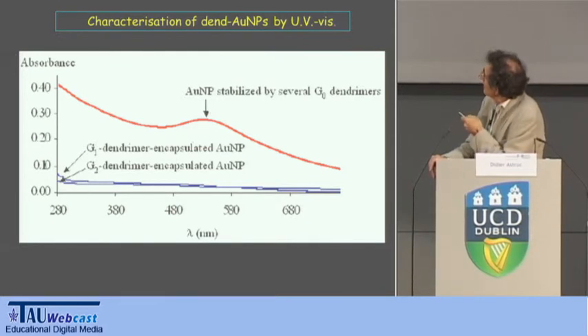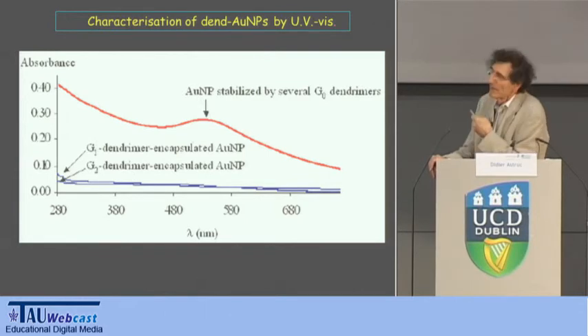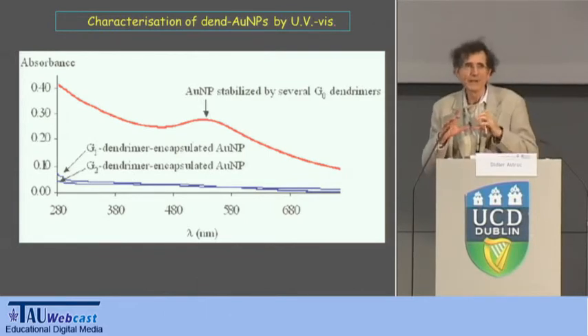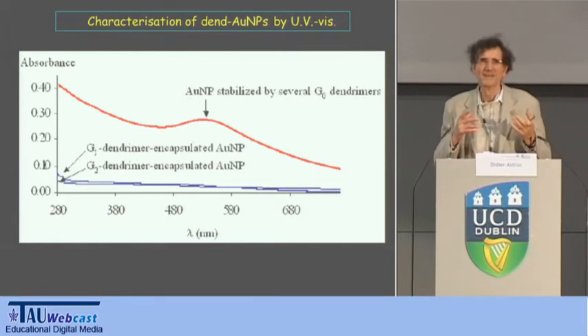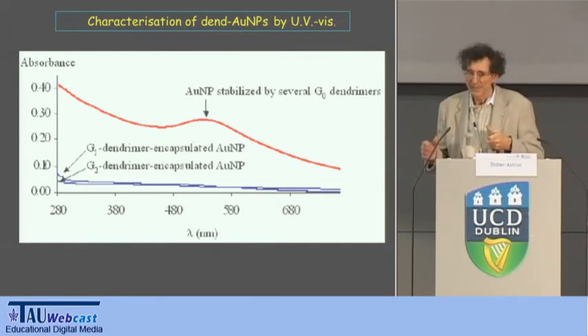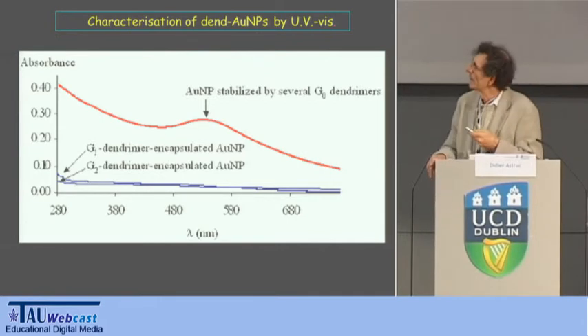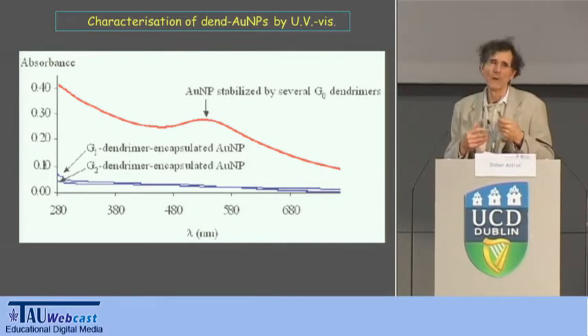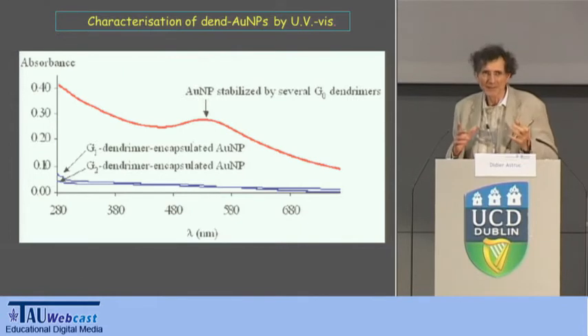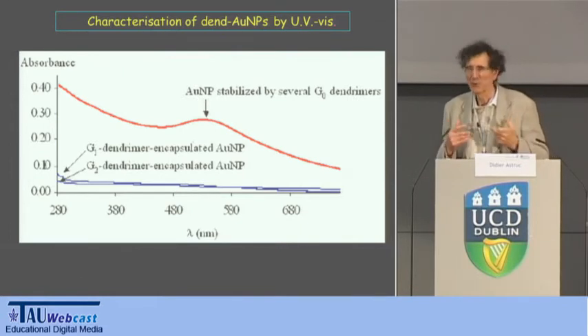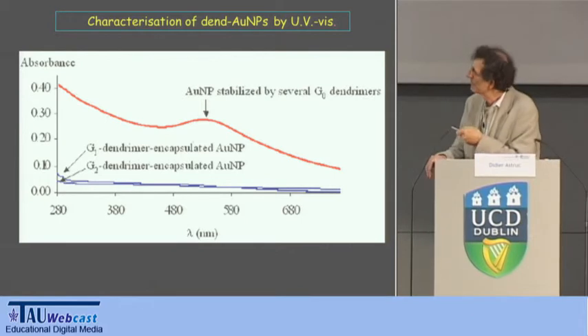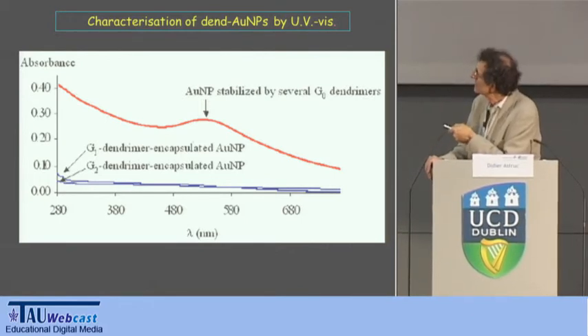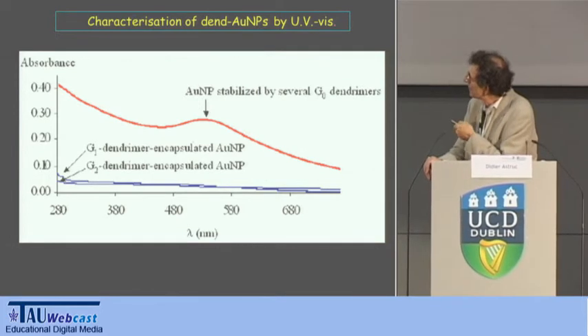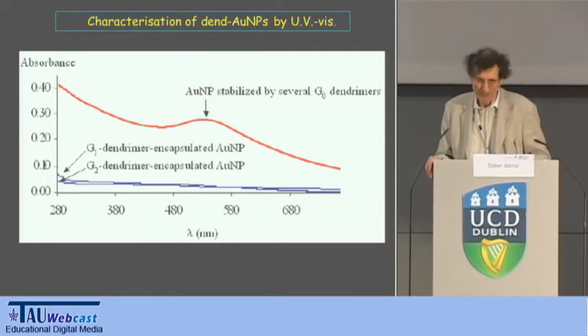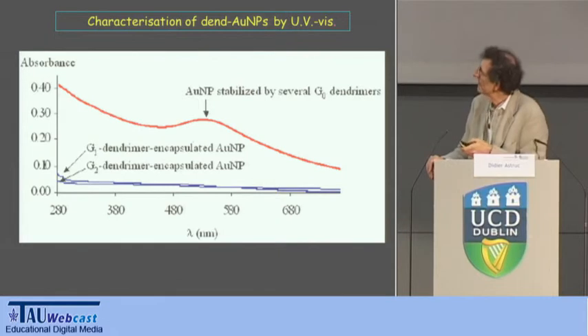The small dendrimer, G0 generation, allows you to get a large nanoparticle. When you are larger than, say, 3 nanometers, you are in the solid state, so you have a plasmon band which is visible. And when you are lower than 3 nanometers or 2 nanometers, say, then you are in the molecular state, so you do not have this quantum dot plasmon band. So you can recognize at once that the large dendrimer encapsulates small nanoparticles, which are smaller than 2 nanometers, because they don't have this plasmon band.